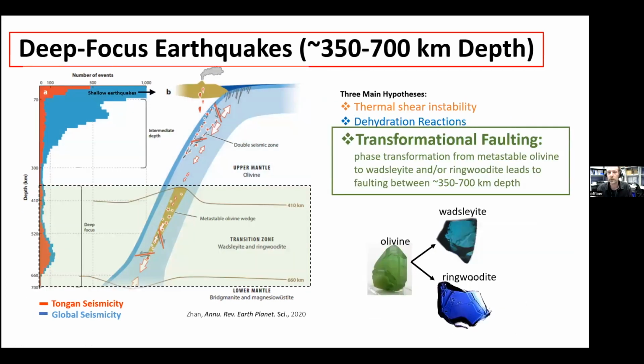But what I will talk about for the rest of this talk is you see as you go below 400 kilometers, you actually see this increase in seismicity. And people have long speculated that this is somehow related to the transformations that happen in olivine at these depths in the transition zone. So the slab is much cooler than the surrounding. So now in the core of the slab, you have cool material that can persist metastably until deeper depths because you need temperature to get the reaction to occur. So you can have metastable olivine that goes down very deep, and then somehow this transformation is thought to lead to earthquakes.